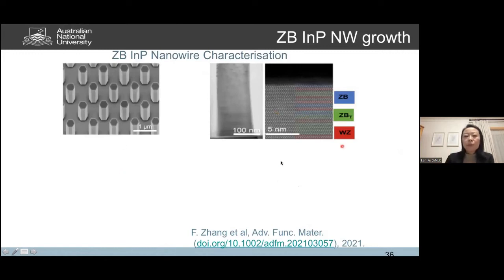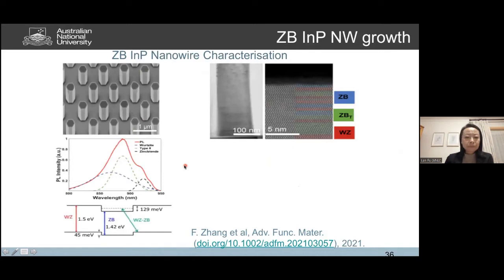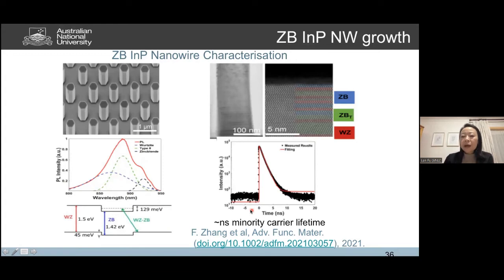And if you look at the TEM, we found that we have this zinc blende and wurtzite mixed phase. It's not pure zinc blende, but it's already good enough to form a very nice uniform nanowire array. And if you look at the PL, of course, we have different PL peaks from the wurtzite segment, the zinc blende segment, as well as the zinc blende wurtzite transition. But despite that, if you look at the carrier lifetime, we can still get a quite nice carrier lifetime of about nanoseconds, which really shows that the nanowire has very good optical properties.